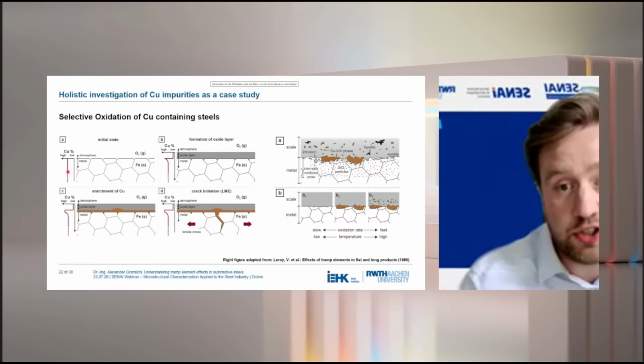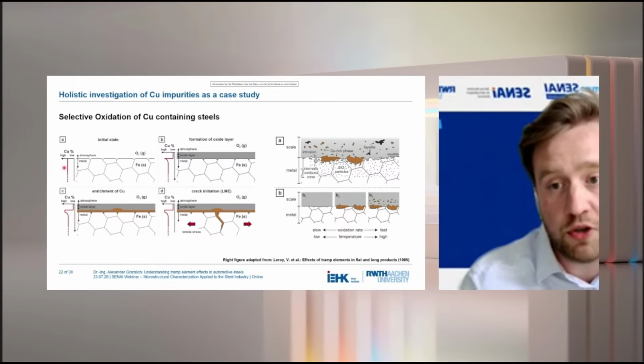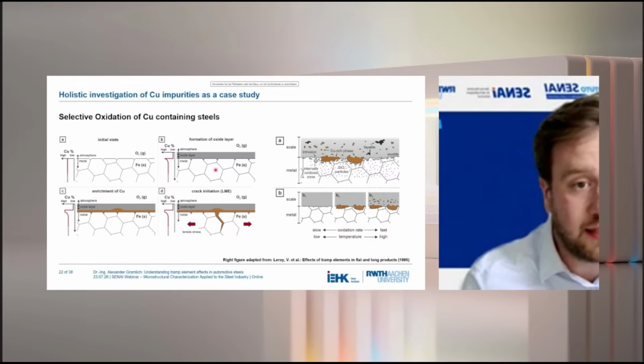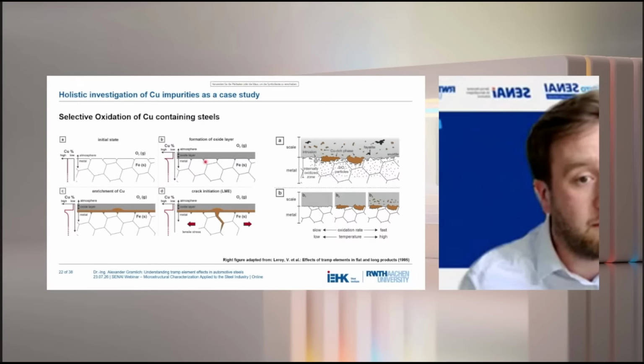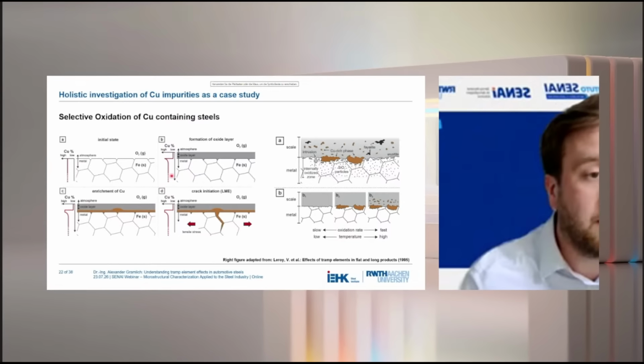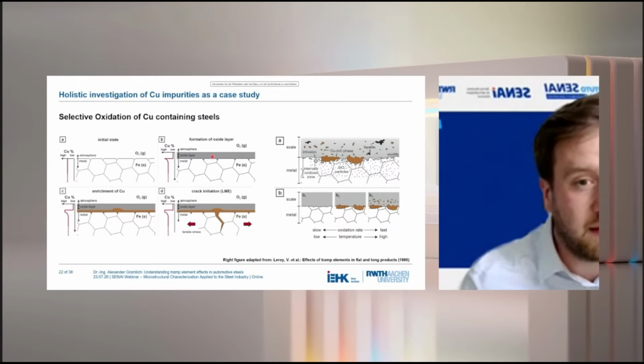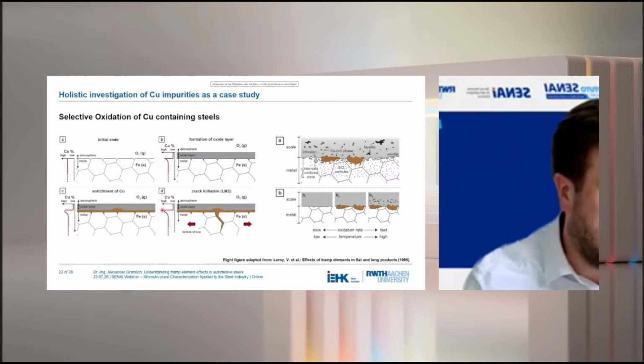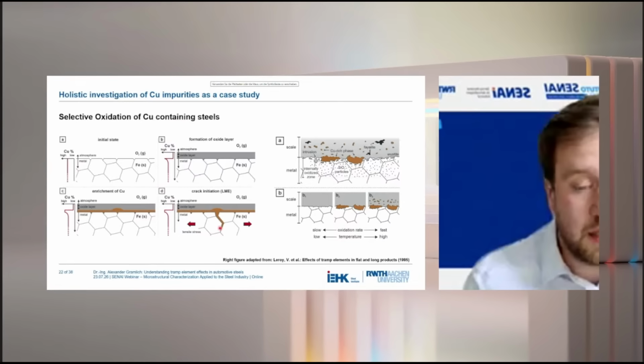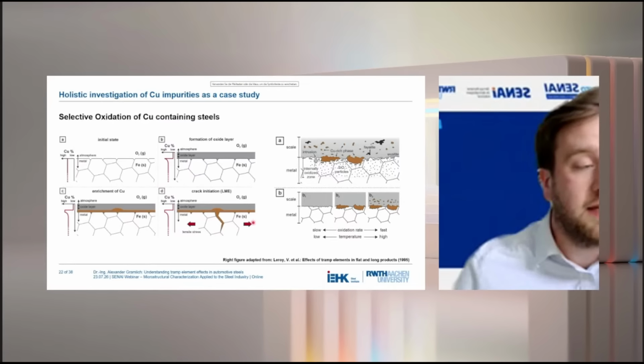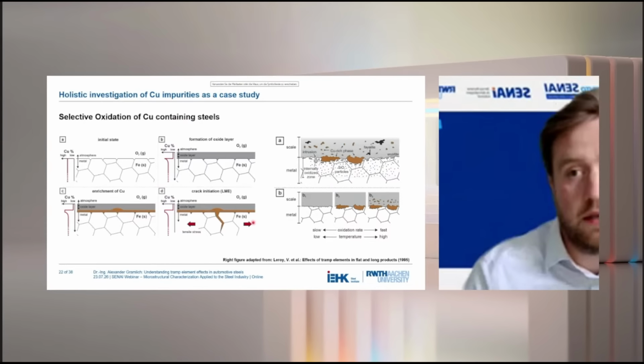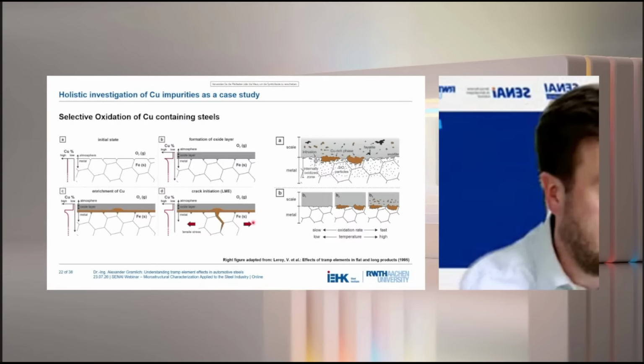You start with an initial state where your copper is homogeneously distributed throughout the matrix. Then your scale layer will form, your oxide, and your copper is not soluble in the oxide. So your copper will enrich between the oxide and the matrix to such an extent that it will form more or less pure metallic copper. And when you then put a stress on the side, basically your copper can penetrate the grain boundaries very easily.